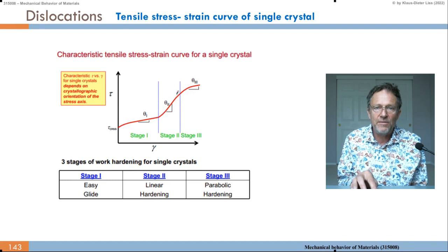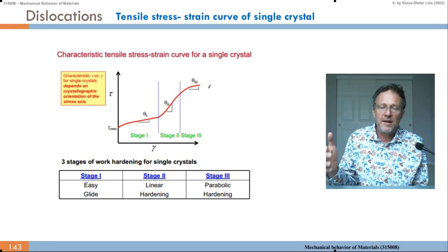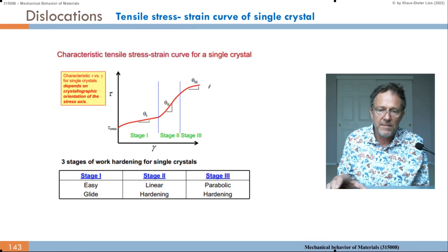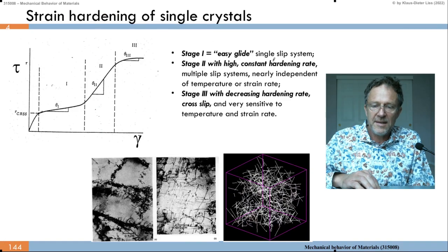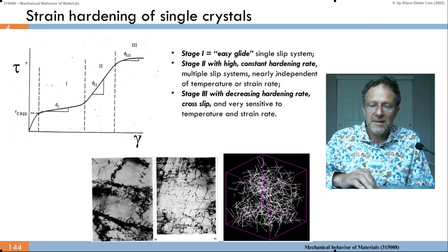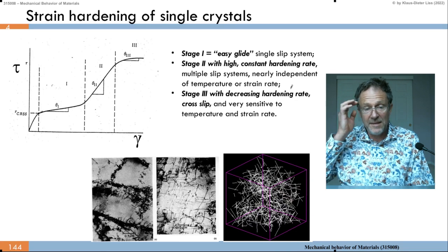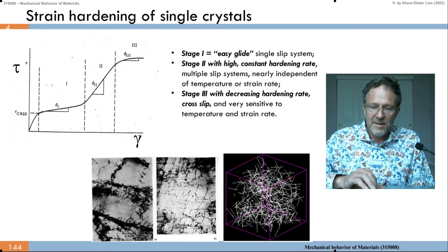When they start interacting with each other, then the material becomes strongly harder. So we have a steeper slope, and eventually we call this parabolic hardening in stage 3, where we have hard material, much harder than in stage 1, but the hardening does not accumulate anymore. It's somehow saturated. The same in this figure here. Stage 1 is easy glide, a single slip system. Stage 2 has a high constant hardening rate, multiple slip systems, nearly independent of temperature and strain rate. And then stage 3 has a decreasing hardening rate. We have cross slip and it is very sensitive to temperature and strain rate.